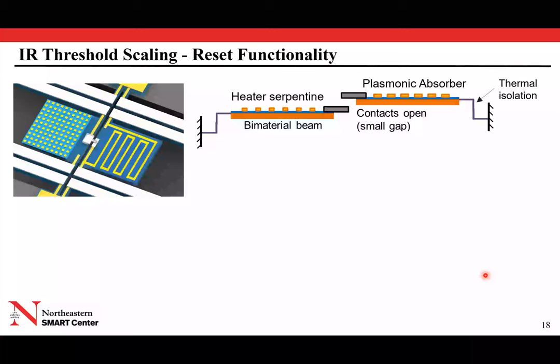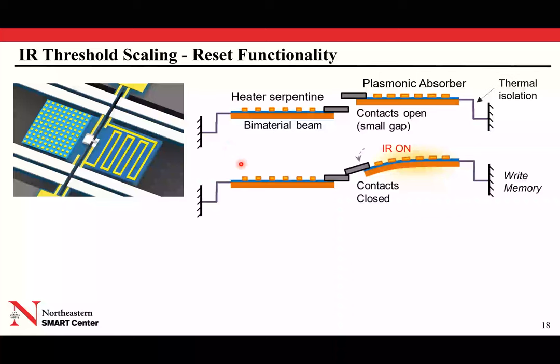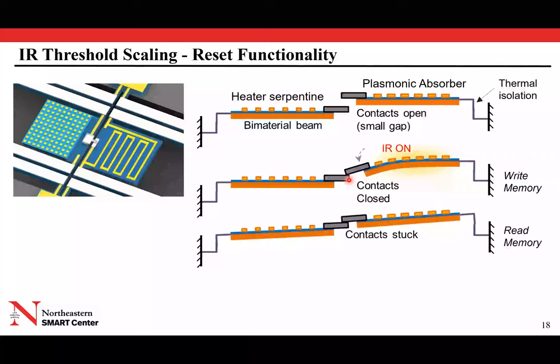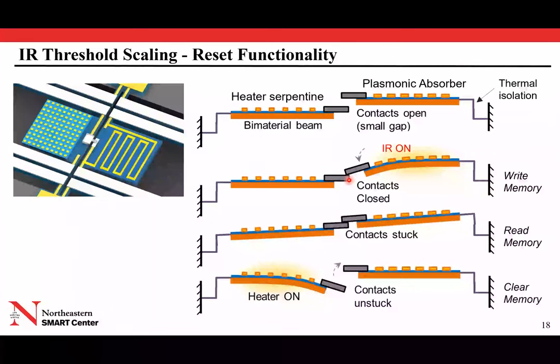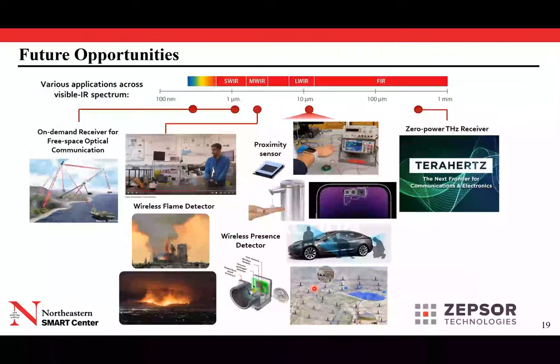And so when we realized that, basically what we did, we integrated a micro heater in the other head of the cantilever, the one that doesn't have the contact tip. And clearly what happens in this case is that even if the device latches on upon detection, we can apply a tiny pulse of energy for a very short interval of time to actually reset the switch. So first of all, we have a device that has some sort of memory function, there is a hysteresis there, and we have these reset capabilities that are very important for some applications.